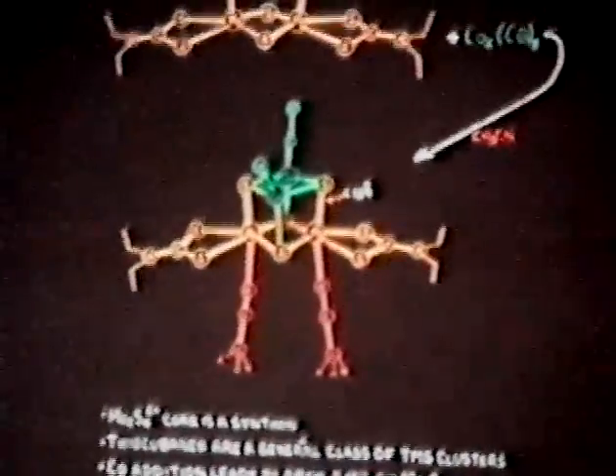Now, it turns out that in parallel studies, we have used cobalt carbonyl as a promoter on some of these crystallites that I talked about before. It's a very effective promoter, and you can measure the activity. So the suggestion then is that this is a model of the structural electronic interaction which occurs at the edge of an MoS2 crystallite.